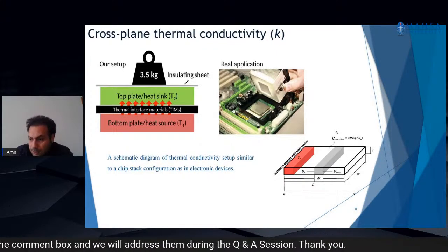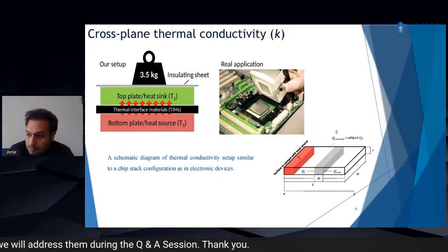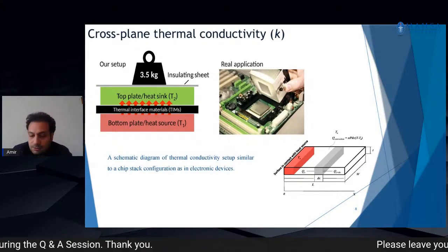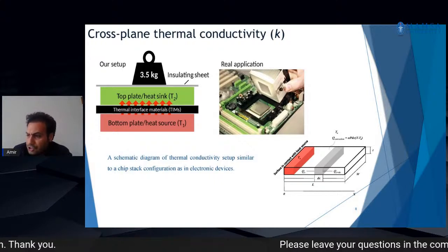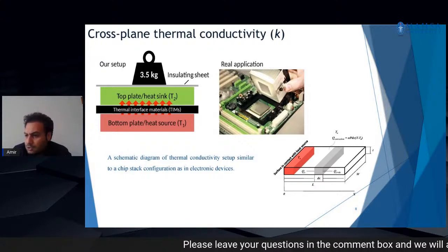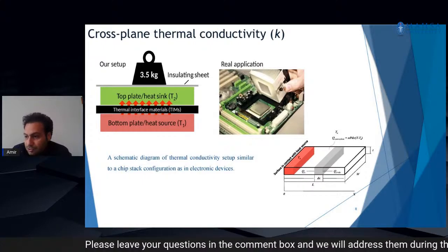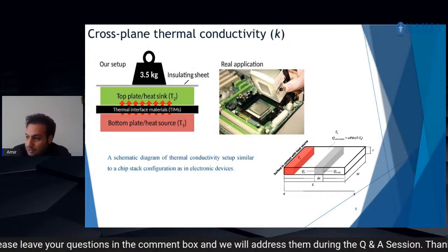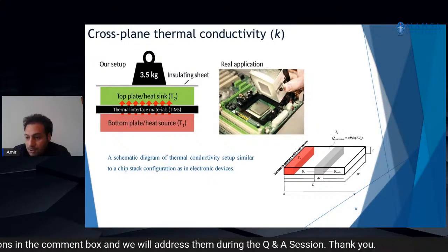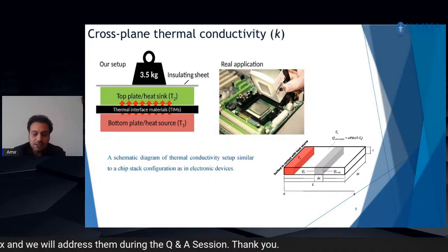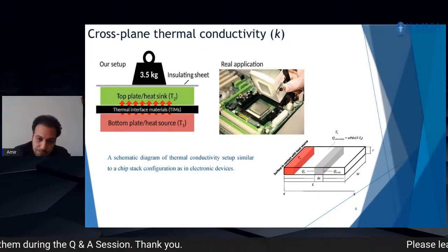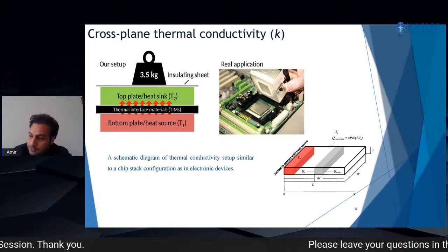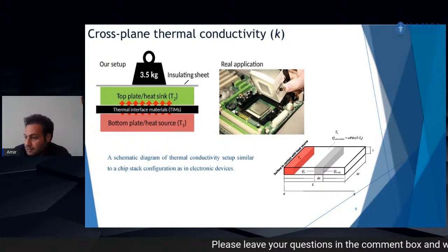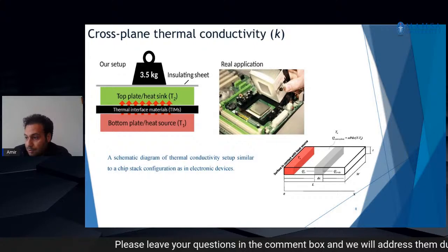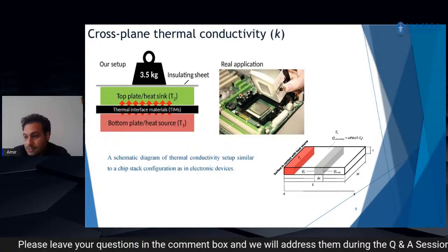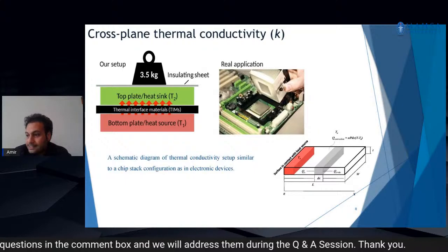Thermal properties of the prepared cellulose graphene nanocomposite and the two reference materials that I told you about, commercial ones of around 6 and 1 watt per meter Kelvin, were characterized by placing them between two steel blocks. The bottom steel block was directly in contact with the hot plate at a temperature around 90 degrees, whereas the top steel block was at room temperature, replicating an electronic procedure and heat sink configuration.